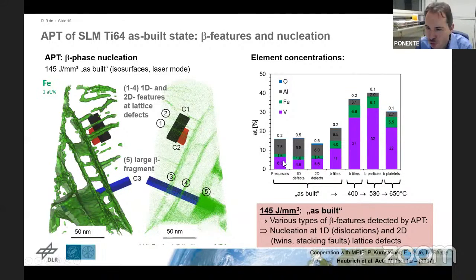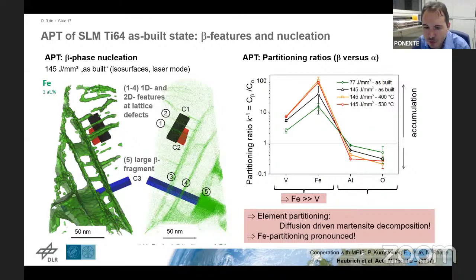And without going into details, you readily see in pink that the amount of vanadium changes dramatically. It goes to a maximum at roughly 530 degrees Celsius. Now this is mass percent, I should note, whereas in the previous HEXRD, it's volume percent from the Rietveld analysis. But again, nonetheless, APT confirms the same trend. There's a maximum of diffusion of beta stabilizers into the beta phase at about 530 degrees, and at higher temperatures, this trend changes again.